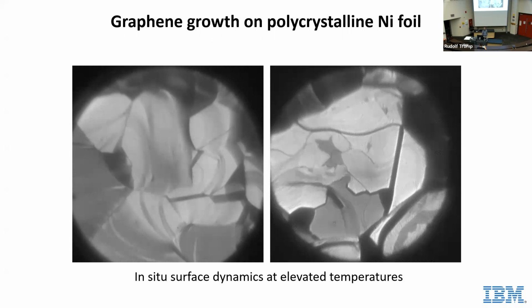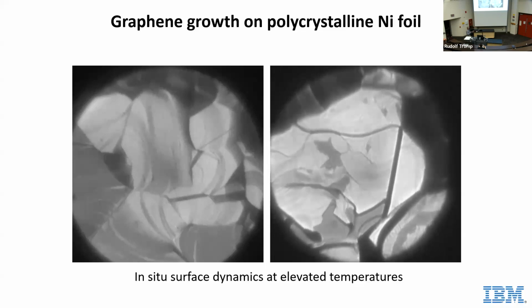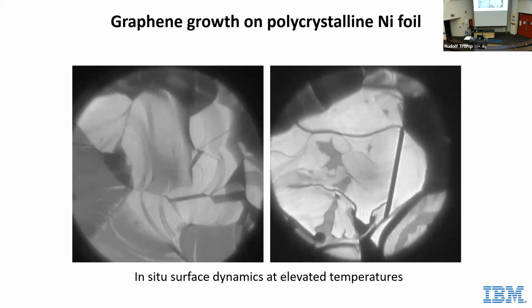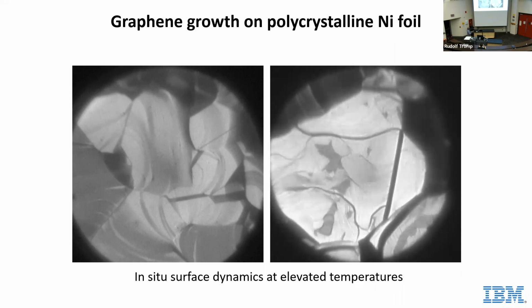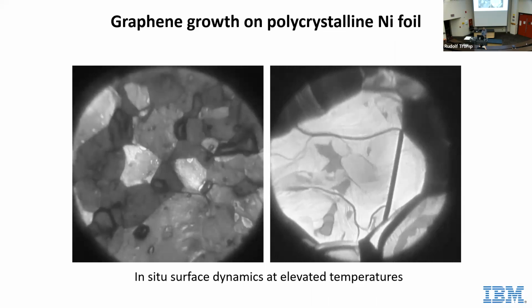Then when we cool the sample down, it turns out there's a little bit of carbon dissolved inside the nickel. And the carbon comes out, and you see how it forms one monolayer of graphene on the sample, right? Just by cooling. If I heat it up again, the carbon will go back in, and so you got this totally reversible thing. And you see that the film slowly closes. I'm not going to run it again, but you will see that as the graphene grows, the nickel steps run away from the graphene edge. There's a lot of physics going on here that you could spend more time on.